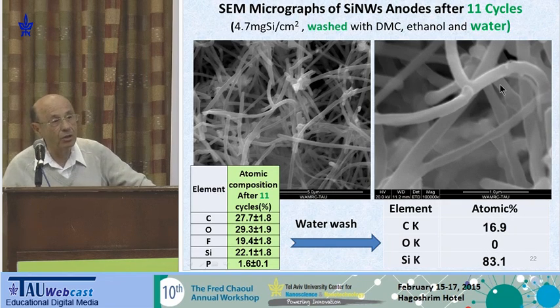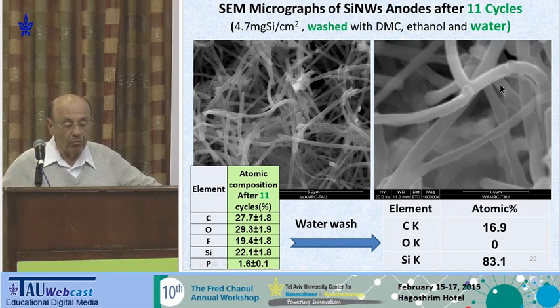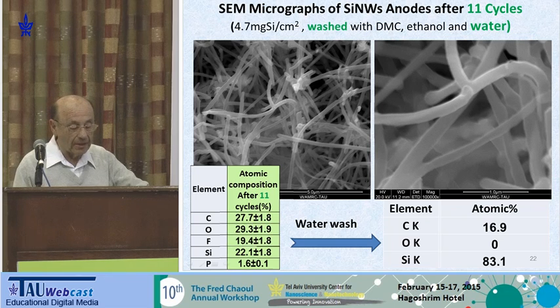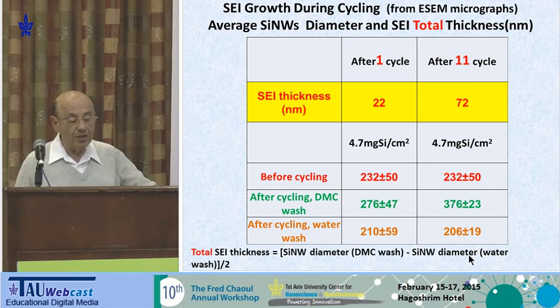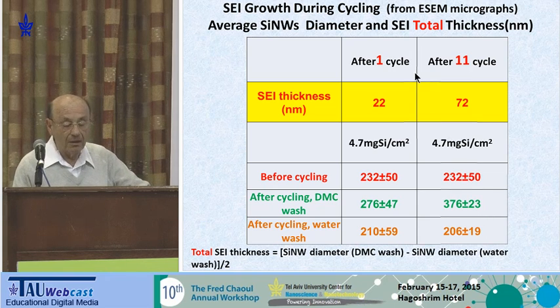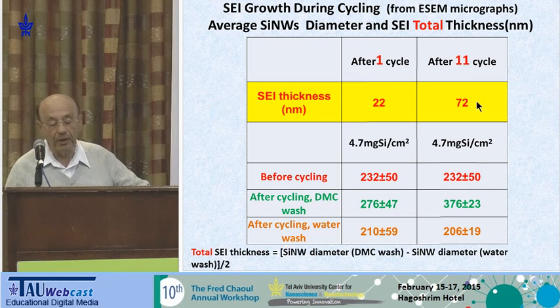When we clean it, we can wash these anodes with water, DMC, ethanol, and water, and we clean out the SEI, we just dissolve it, and instead of this kind of composition, we got only silicon and carbon, and we don't have fluoride and phosphorus, and silicon goes up to 22 to 83%. So you see that we have some water-soluble SEI on this fiber or nanowires. Now we measure the thickness of the SEI during 11 cycles. It goes from 22 to 72 only during 11 cycles. And as I said, we run it to 200 cycles, and it goes much more.